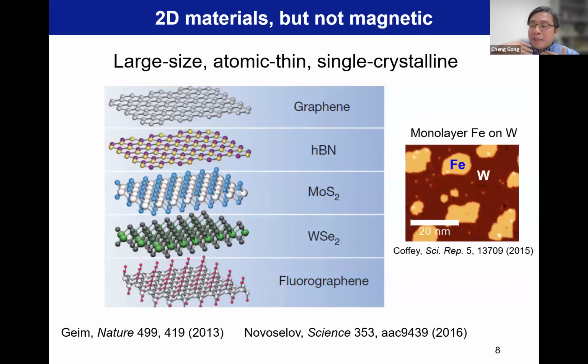But if you look at the traditional magnetic film, for example, if you use MBE to grow a single layer of iron on a substrate, for example tungsten, nominally it's one layer or two layers, or sometimes from papers you can even see 1.3 layers or 1.5 monolayers. That means this layer number is an average layer number. If you look into the detail, you will find it's actually nucleation-based growth. There are many islands. Within each island, it could be uniform in thickness and single crystalline, but you have tons of such nano islands, each on the size of tens of nanometers. So certainly it's different from 2D layered van der Waals materials.